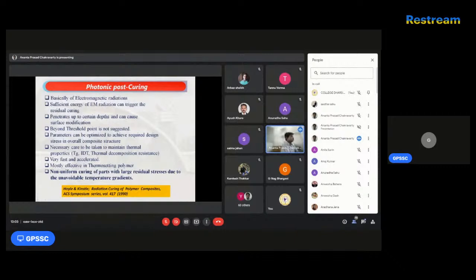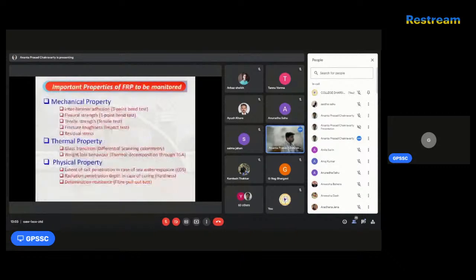Obviously I have told the typical problems associated with these composites and what kind of investigations are required for their improvement, and through that, what characterization techniques we want, that we have generally known. So I have listed them. To know the mechanical properties of such FRP-based composites, we have to go for interlaminar adhesion through 3-point bend test, flexural strength through 3-point bend test, tensile strength through tensile test, fracture toughness, and residual stress.